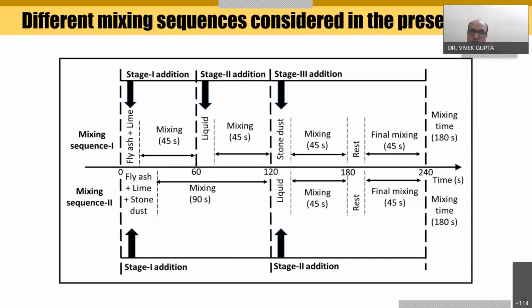In the mixing sequence 1, in stage one we have added the fly ash and the lime, and in stage two, after 45 seconds, we have added the liquid as a second stage addition, and in the third stage we have added the stone dust.